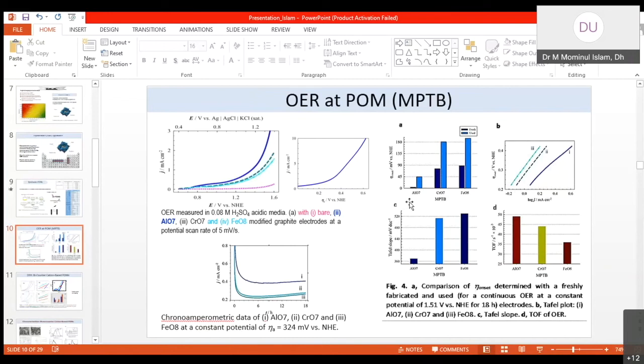If we see this, the aluminum-based catalyst, this is the chromium-based, and this is the iron-based catalyst. Among these, the aluminum-based catalysts give a low onset overpotential as well as a low Tafel slope compared to the other two, and also a high turnover frequency, indicating that the aluminum-based catalysts give high catalytic performance.